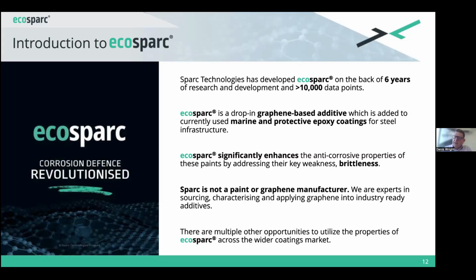And we've also got the graphene dispersed in a number of other polymers as well, so that the polymer of use is indigenous, or comes from, as best possible, the polymer that is within the coating system, because that means that all the customer is putting in is the graphene, and they're pulling out a little bit of polymer to take into account the polymer that comes in with the additive. It addresses the brittleness and it improves the anti-corrosive properties of it. There's a cause and effect there. The effect is the anti-corrosive properties are improved.